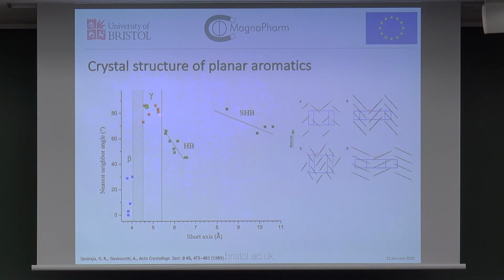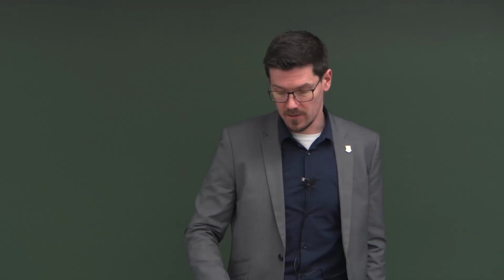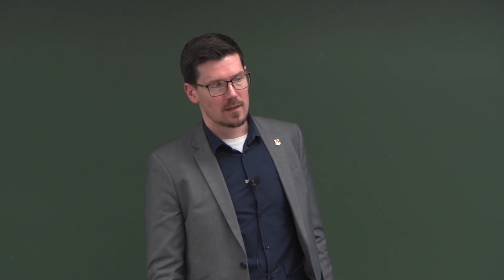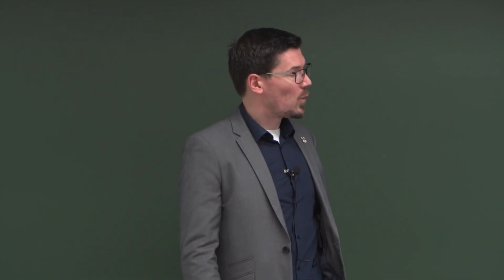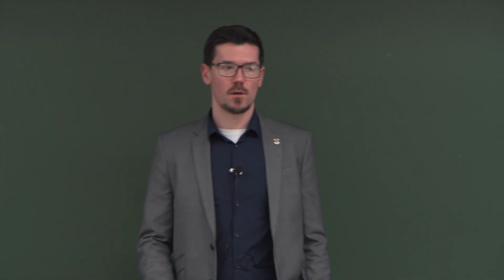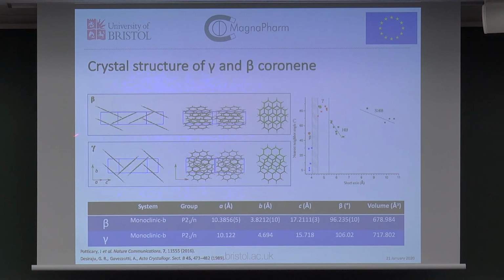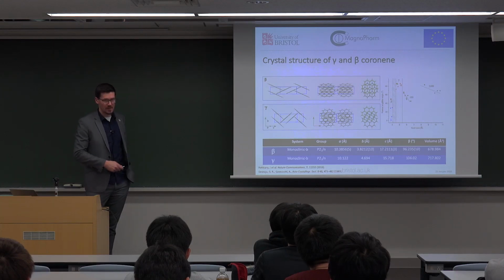And coronene sits right there where that green spot is, up in the gamma region. So coronene adopts a gamma herringbone structure. When we did single crystal diffraction on the new orange crystals, what we found was that it had a shorter B-axis, and the angle in which these molecules sat next to each other had changed. So when we plotted that on the graph, we found that we actually had made a new polymorph of coronene here in the beta region. So we called it beta coronene.